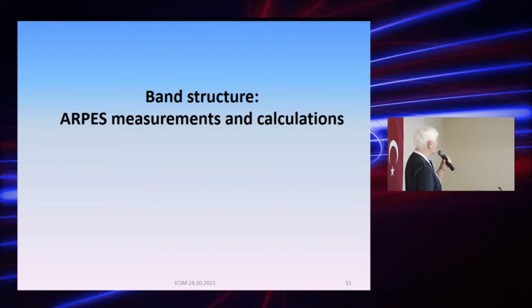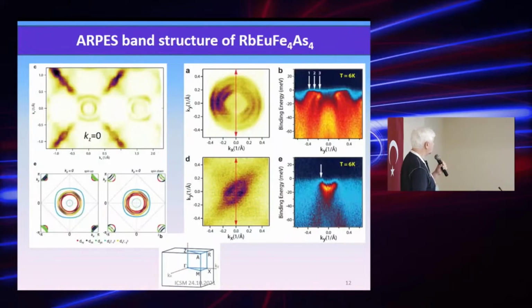Now, first of all, we have to take a look at the band structure. Indeed, as it follows from ARPES measurements, it consists of several cylinders which are directed perpendicular to the screen, and at some points of the Brillouin zone we can identify 3 cylinders. At other points, 2 almost coincide, so we see 2 cylinders only.